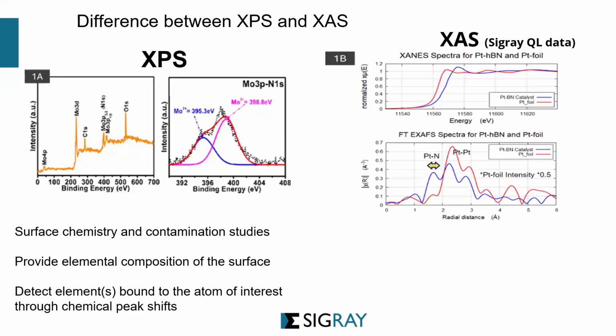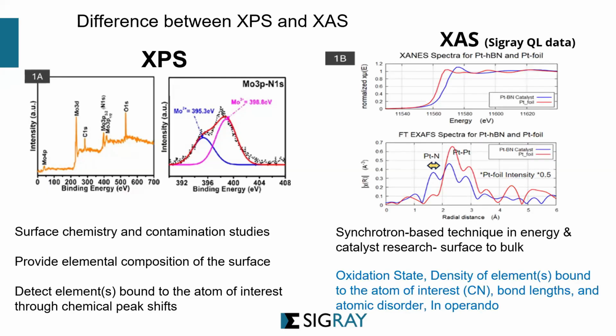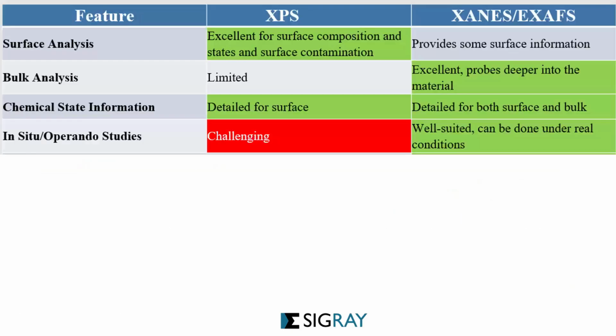Whereas in XAS, you have the ability to look at oxidation states and density of the elements from the surface to the bulk of that material. Things that are bound to the atom of interest, bond lengths and other things, and it can do in operando types of characterizations that are not possible with XPS. So to summarize that quickly in a table, we will say that XPS is excellent for surface composition and surface contamination, but not for bulk.